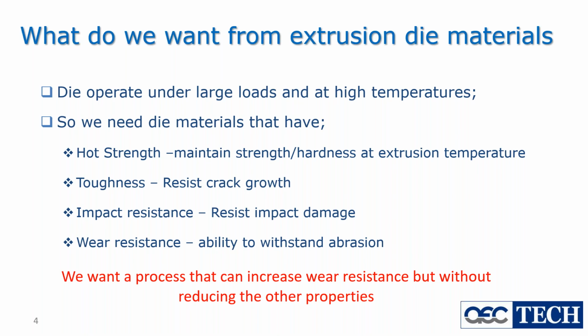It needs to have some toughness. It needs to resist crack growth. I've seen a lot of dies with little micro cracks in them. In good steel, those micro cracks don't grow too large, and they don't really cause the die to reach the end of its life. We need impact resistance. Those dies get bashed pretty hard sometimes. That's without people taking sledgehammers to try and get them out of the die rings, which always makes me cringe slightly. And we need good wear resistance, because we need them to withstand abrasion and adhesive wear in the extrusion process.